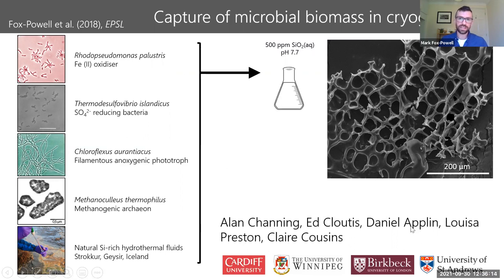And we effectively did a very similar experiment, but we included microbes. A few different pure strains of microbes and some natural communities. And you can see on the right-hand side here, this is a silica lattice, an amorphous silica lattice, precipitated out within brine veins between the ice crystals that have precipitated. It's a very similar process, but we're just looking at a simple brine containing silica.